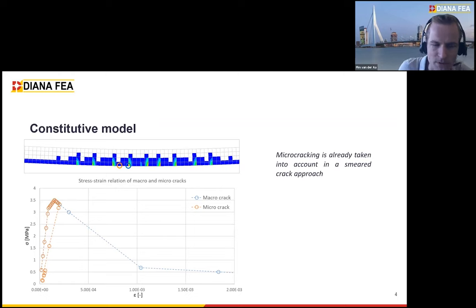In the top picture, you see some cracks in a finite element model, and this was modeled with a smeared crack approach. The blue circle highlights the macro crack, and what you see is that it just nicely follows the stress strain diagram. But between the cracks, you can see the micro cracks, and the micro cracks basically unload at some moment. This already shows that micro cracking is already in the analysis, so there's no need to take that part into account.